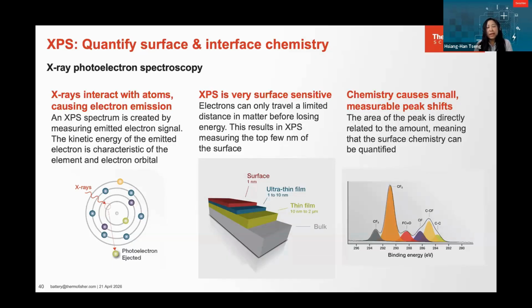And so in this way, the peak for a particular element will move accordingly depending on the actual chemistry of the surface that we look at, and that enables us to measure the composition of the sample. Next slide, please.